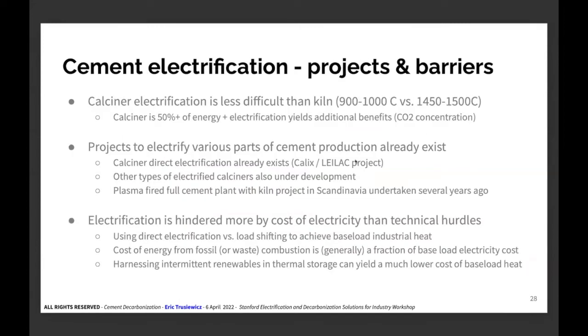Why? Because if you look at electrification generally, the calciner is less difficult to electrify than the kiln. The calciner operates around 900 or 1000 Celsius, so you don't have the same material issues that you would if you're going to try to heat things to a 1500 Celsius process. So that's a lot easier. The calciner is actually more than half of the energy generally in a cement plant, because calcination, in addition to the heating, needs a lot of energy to take place to break that bond and to release CO2.